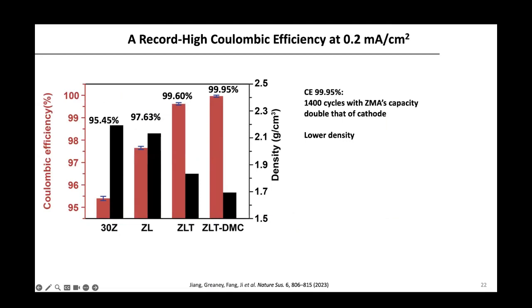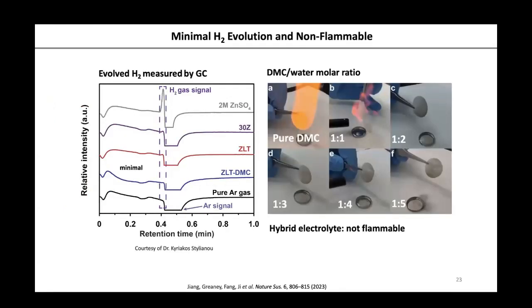Coulomb efficiency. So now we have the Coulomb efficiency of 99.95. This is the goal we have. That means you can have a zinc metal anode that is reversible for a long cycling of zinc metal batteries. Now, we also used gas chromatography to observe how much hydrogen gas is produced with different electrolytes. This is the conventional zinc sulfate electrolyte, widely used. It's not very stable with zinc metal. It's producing a lot of hydrogen gas. Now, if you look at the peak here for hydrogen gas, in the concentrated zinc chloride you have a bump here, and now with DMC added, that bump is almost gone.